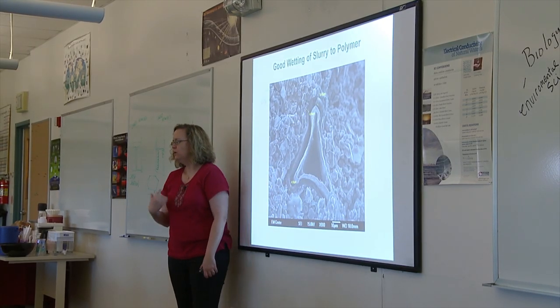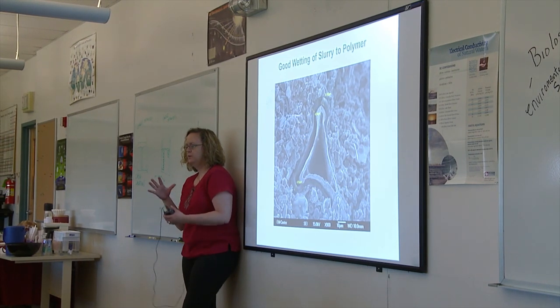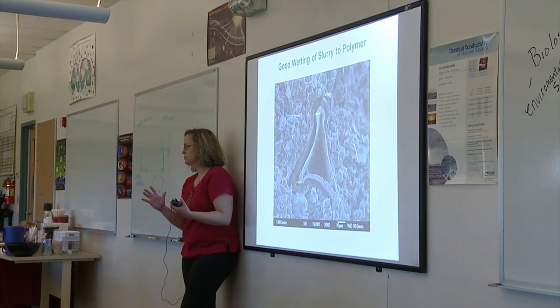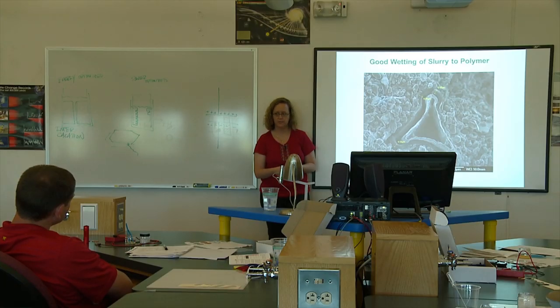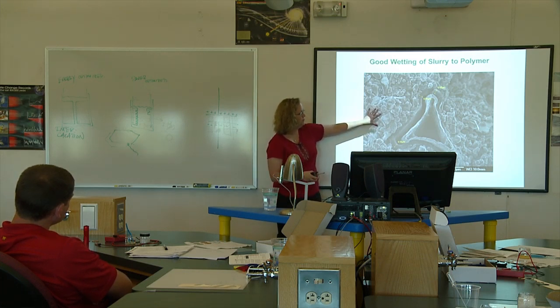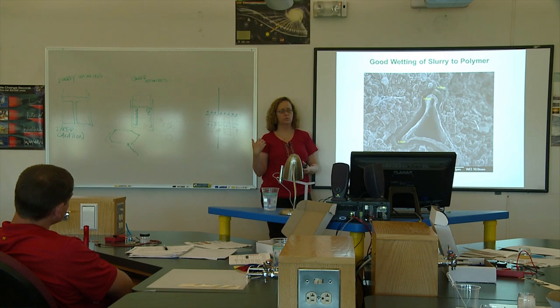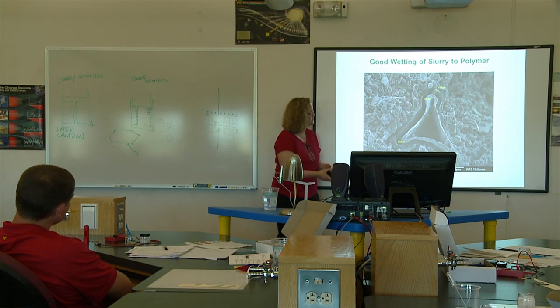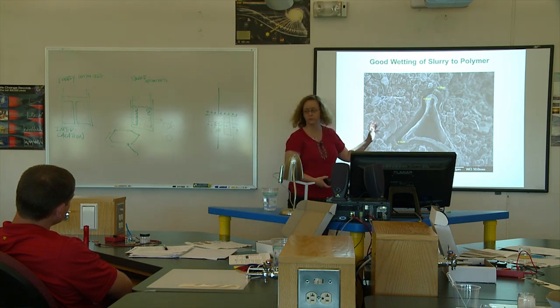So now the way we make our polymers, it actually chemically bonds to the copper antimonide as it's growing so that you can't pull it away. We have gotten better at the deposition, so now it's thinner, 750 nanometers. But what this is really showing is that this cathode we designed so that it could wet really well to the polymer but not dissolve it, so that it would get pulled in. And you can see that it does, it wet really well, it makes really good contact.